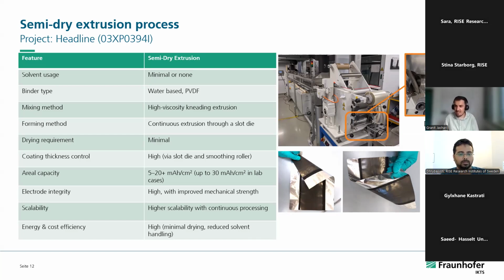And then the coating thickness control is high, since we are using a slot die, which is also used in the tape casting method. And we are able to have a really wide range of areal capacity which we could produce on the electrode, which is not the case with tape casting, since when you are doing high areal capacity electrodes, you have a lot of cracks, since the film of the electrode is really thick.